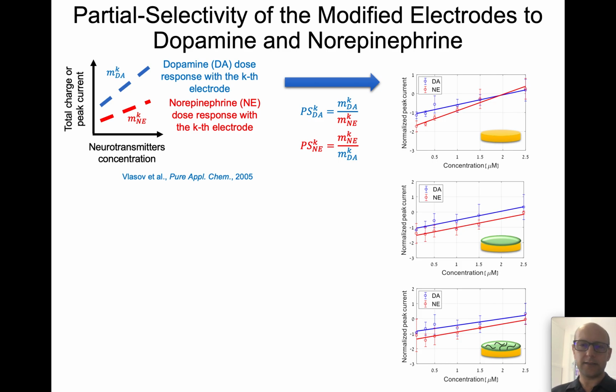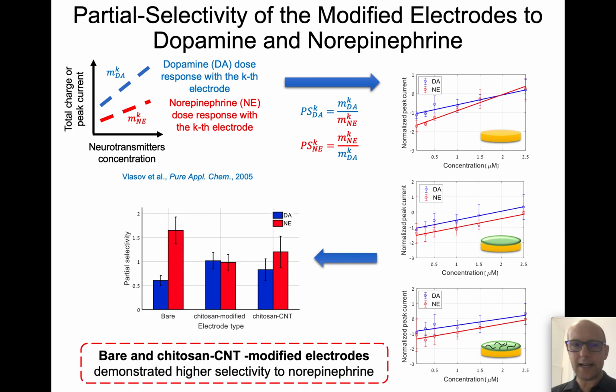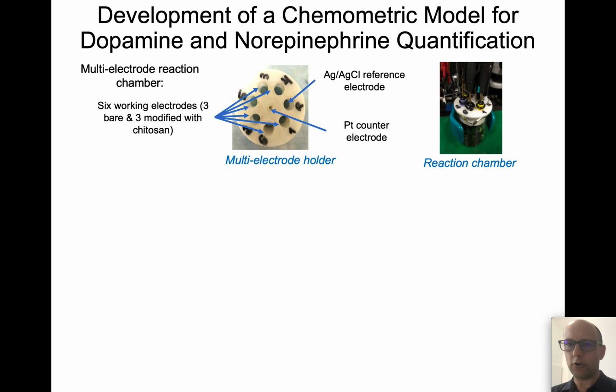And for that, we measured the dose response characteristics for either bare, Chitosan-modified, or Chitosan-Carbon nanotube-modified electrodes, and we calculated the partial selectivity. We showed, very interestingly, that the bare electrode was more selective to norepinephrine than dopamine, and so were the Chitosan-Carbon nanotubes, but the levels of selectivity were different between the bare and the Chitosan-Carbon nanotubes for each one of the molecules. While the Chitosan-modified electrode didn't show any different selectivity to either dopamine or norepinephrine. So that's why we can use these multiple electrodes to generate a set of cross-reactive electrochemical signatures in order to develop the chemometric model that will identify the fingerprint of the molecules.